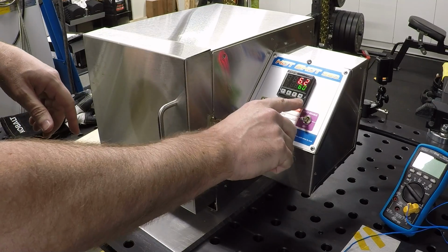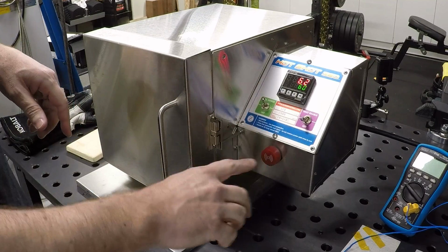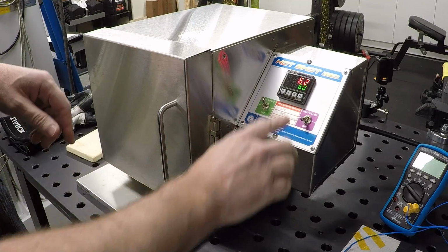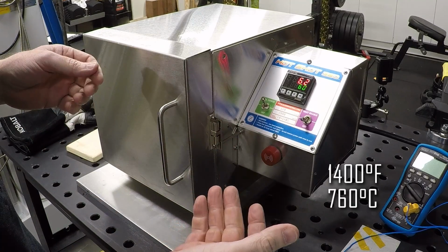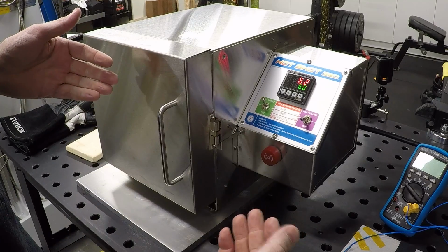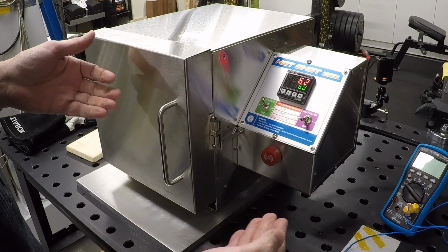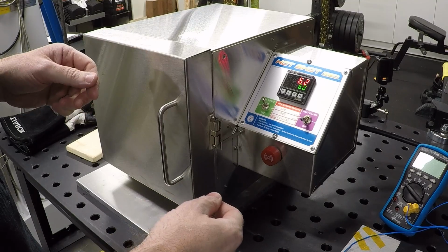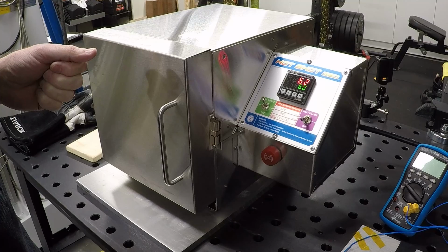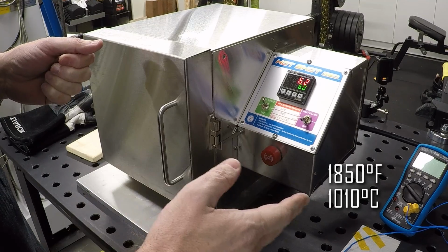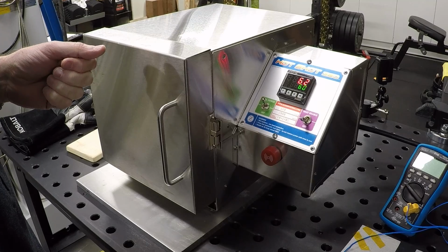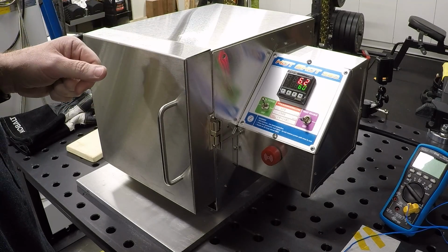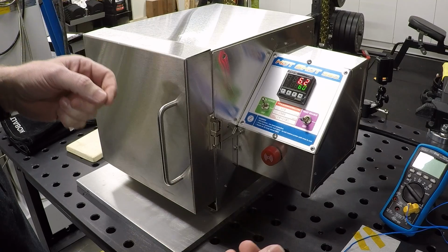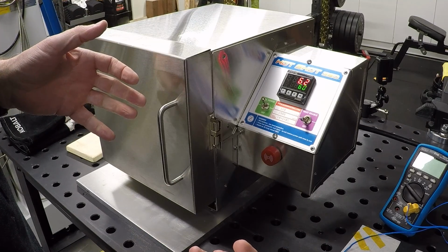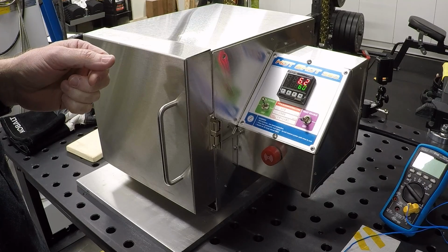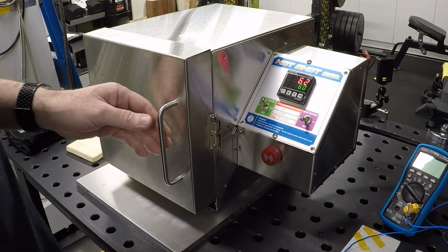This one has the N480D, which is the ramp and soak controller, and I have it pre-programmed to ramp up to 1400 degrees for a preheat. Over the course of an hour, then it will soak at that preheat temperature for 30 minutes. Then over the next 30 minutes, ramp up to the heat treat temperature of 1850. It'll soak there for half an hour and then power off. So the entire process is, what, a 2.5 hour heat treat cycle. Because these parts are so thin, that's probably overkill, but that's quite a bit faster than the 5 to 6 hour cycle recommended by the manufacturer.